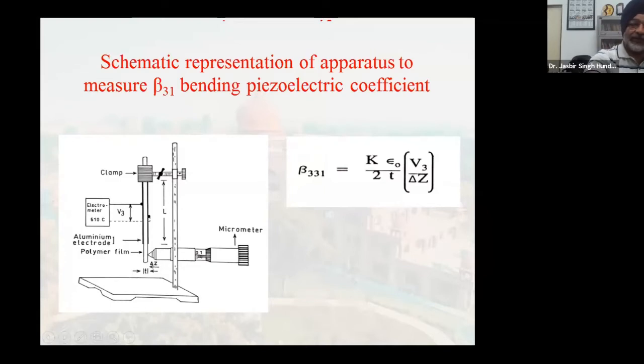When you rotate this micrometer, when it moves in the forward direction, the film bends. And by bending, you'll get piezoelectric current moving in the electrometer, and we are able to calculate the bending piezoelectric coefficient. Whereas this is the dielectric constant of the material, this is voltage that you get here when this film is deflected. Delta Z is the deflection, and T is the thickness, and K is some constant for this particular setup. Okay, so this is the apparatus which we use for measuring bending piezoelectric coefficient.